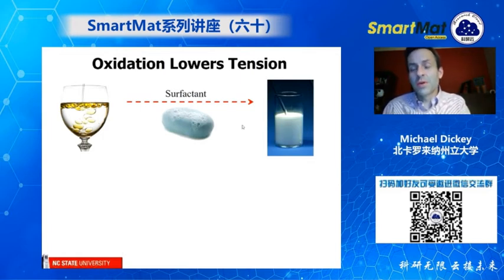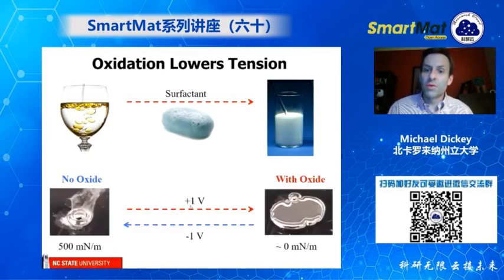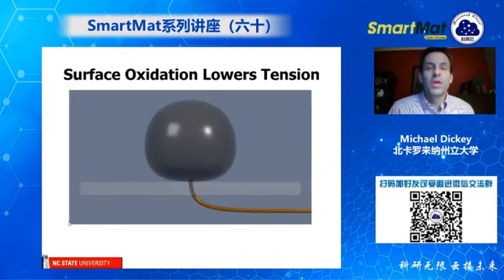Now, in the case of soap, it's very easy to add the soap, but very difficult to remove it. In our case, we apply 1 volt and we deposit the oxide and it flattens because it's got a low surface tension. Basically, gravity squishes it down. But then we can completely remove it using -1 volt and it goes away. So it's completely reversible. And it's a huge, huge change in tension. It's really hard to appreciate, but this is like a record setting. Nobody's ever achieved such a large change in tension using soap, for example.